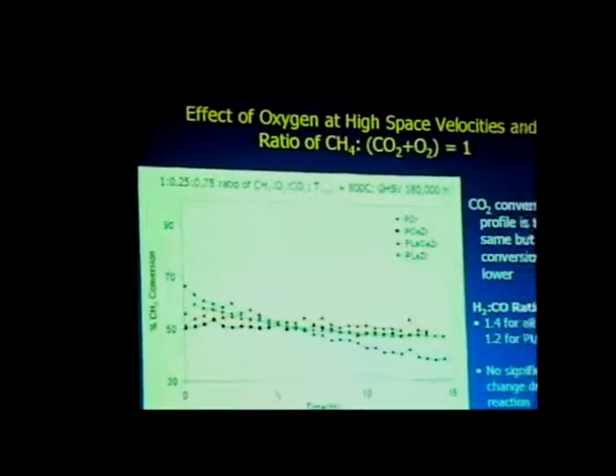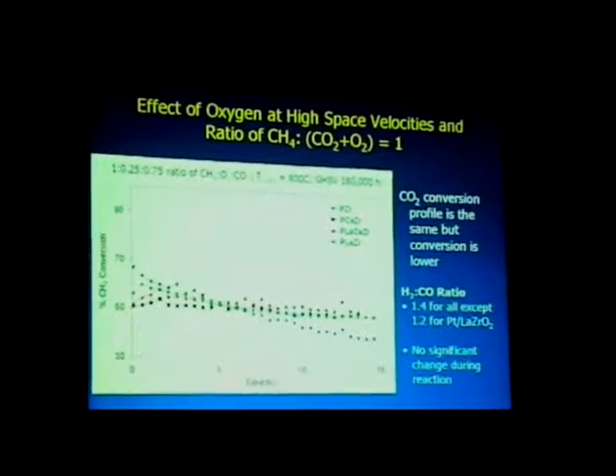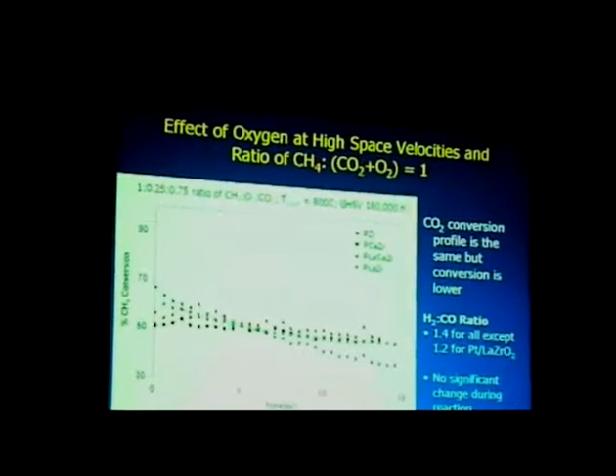If we change the amount of oxygen and change the methane to the CO2 and O2 ratio, we again see very little difference in the promoted materials